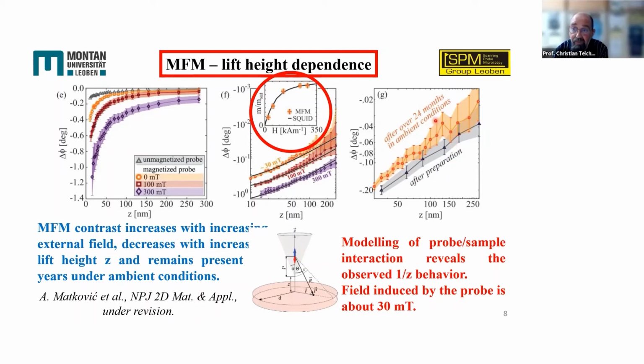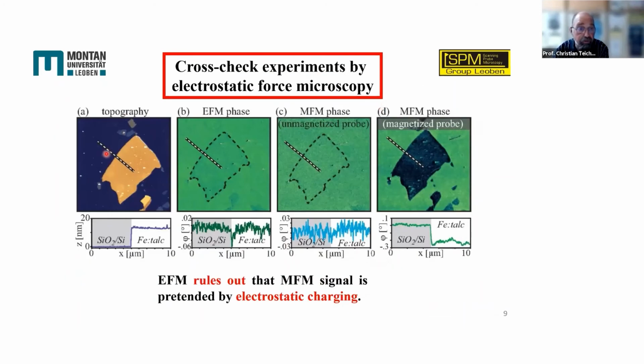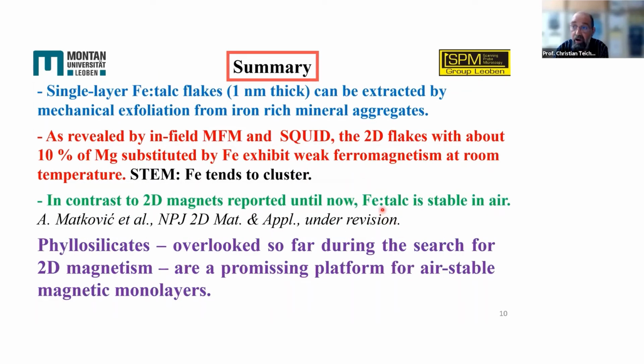Here you see that even after 2 years under ambient conditions, this material still shows this behavior, so weak ferromagnetic response. Just to show that we have a real MFM contrast: we use EFM, electrostatic force microscopy probes, and we do not see a contrast. Also with an unmagnetized AFM probe, we do not see a contrast, but switching back and forth to MFM probes, we clearly see a contrast, so we can rule out electrostatic charging.